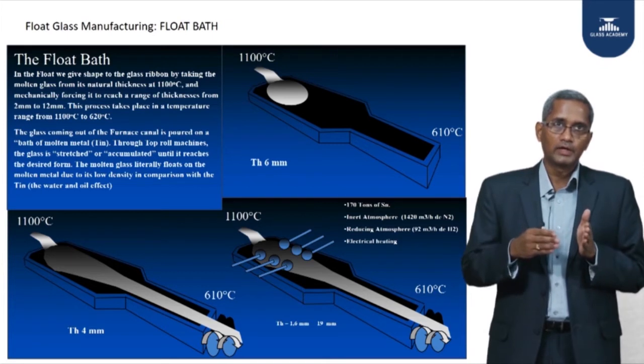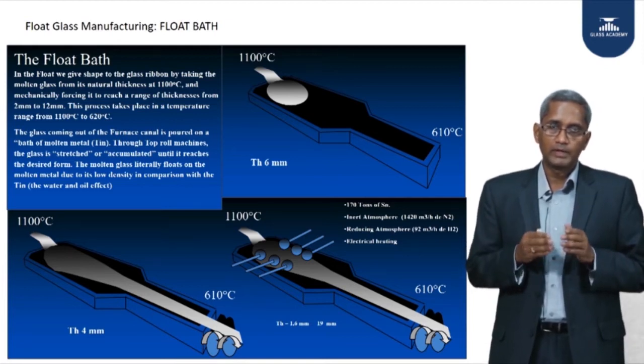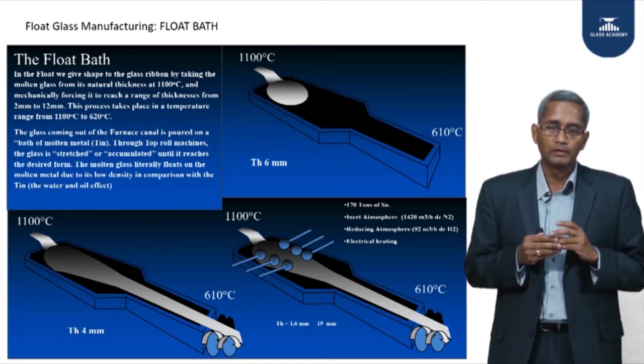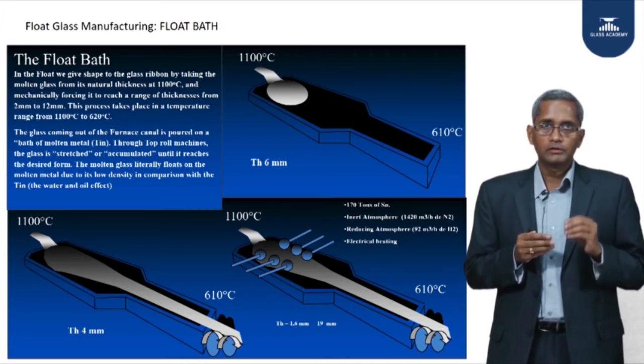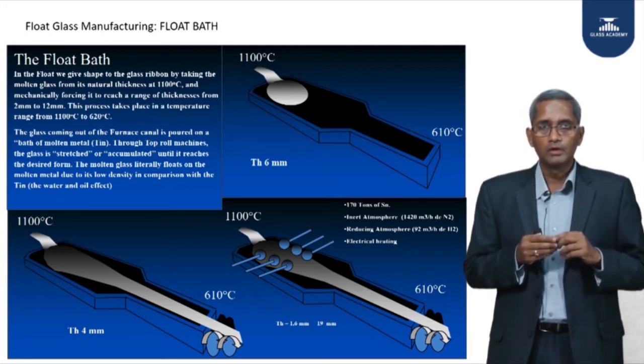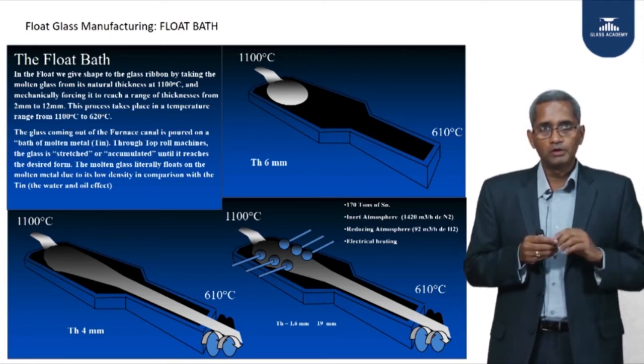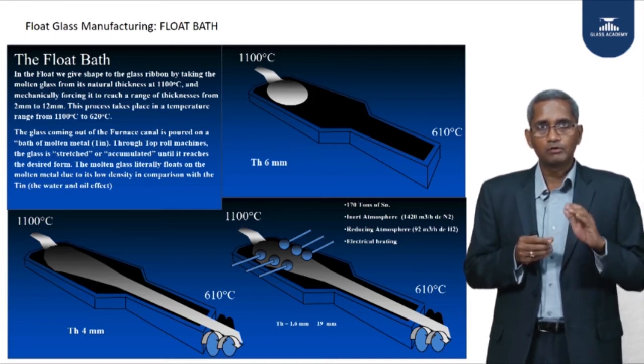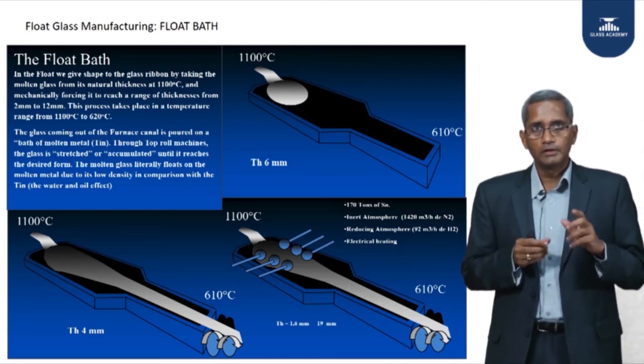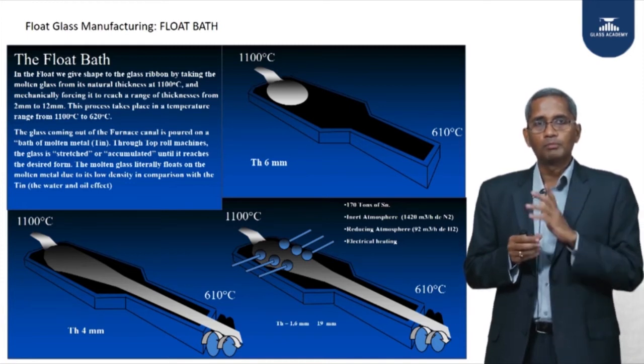Closing the angle to a negative angle pushes the top roll head inward, making the glass thicker. The second parameter is angle. Additionally, the top roll can be moved in and out, and the penetration — how much nip or force is applied on the glass — can be controlled via an up-and-down mechanism. Using these four parameters — speed, angle, in/out position, and nip — we provide the desired thickness of the glass.